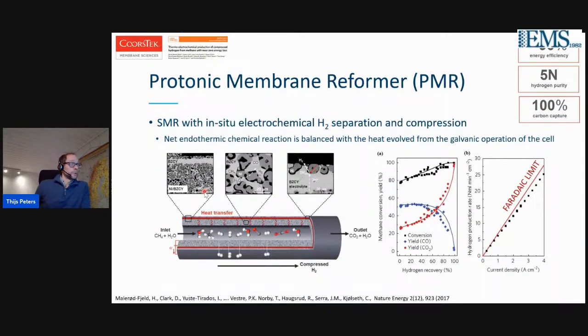I'd like to focus then on the proton membrane reformer, which is an integrated high temperature membrane process for combined hydrogen production with CCS, where the in situ removal of hydrogen shifts the equilibrium towards the hydrogen side, and thereby, the moment you remove a lot of the hydrogen, you convert all the methane, and you get a very high CO2 yield. The nice thing of this is that the membrane process even compresses the hydrogen because it's compressed electrochemically, and the heat that is produced is then supplied in situ for the endothermic SMR reaction.